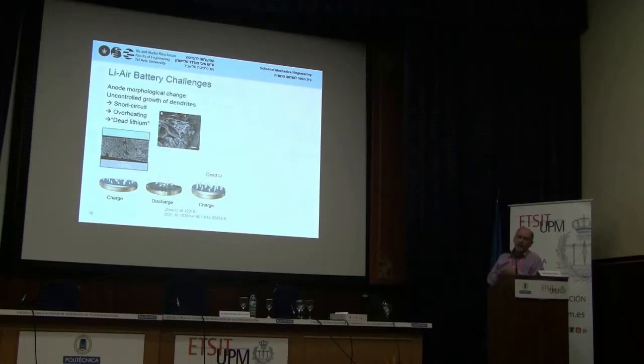The problem is that when the lithium goes back to the original electrode, it doesn't plate the electrode in a very smooth and nice layer as it was before. It creates all of these strange structures that are called dendrites, and this is something that's very difficult to avoid. And because of these structures, they penetrate into the membrane, create shortcuts, and they also can create situations like this, that the dendrite grows and contracts, and then pieces of lithium are suspended in the middle somewhere, and there is no electrical contact to these pieces, so this lithium is lost. So actually a rechargeable lithium air battery does not exist, or at least those that have been tried are not really working.